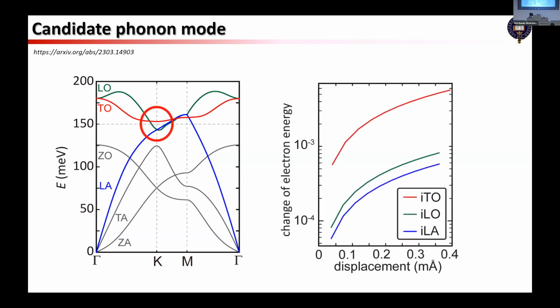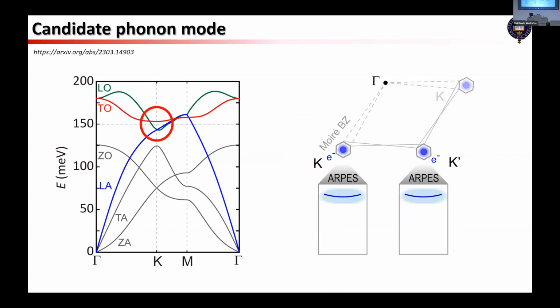So we collaborated with Shida's group, and he did some calculation, and his calculation result really did show that this red phonon branch, the interlayer and transverse optical phonon, indeed has a higher electron-phonon coupling strength. That agrees with our intuition that this flat band has higher density. And so how does this replica happen? We can see there are flat bands from the K and K prime points, and if you turn on this K phonon electron-phonon interaction, you can see this K flat band, after scattering with this phonon, goes to the K point as a first replica, and then will scatter back. And similar things happen from the K prime to K, and then go back to K prime.